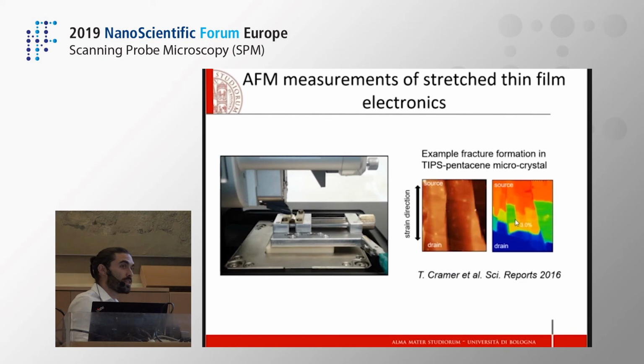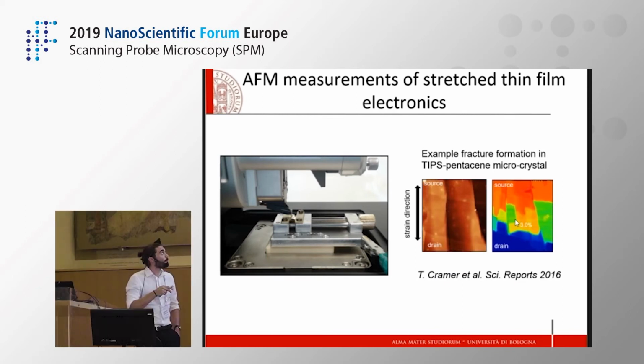In order to understand this behavior, we performed an AFM measurement under strain, using a mechanical stage that was able to keep the strain of our polymer while we perform AFM images, as done in a previous work of Professor Cramer shown on the right.